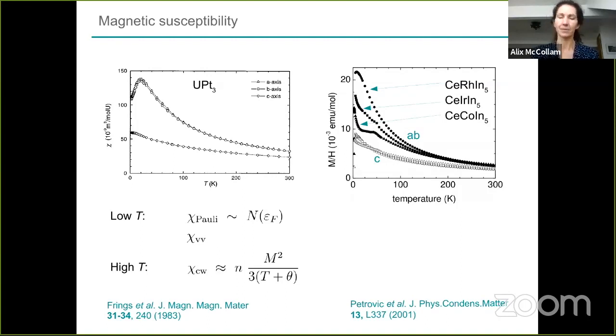So okay, let me clarify. When you measure the effective mass in the de Haas-van Alphen effect, you're measuring the temperature dependence of the Fermi function effectively, and that's where it's coming from. But that's for a Fermi liquid. If you don't have a Fermi liquid, you have a different form of the self-energy that goes into the expression for the de Haas-van Alphen effect. And it will give you maybe a slightly different temperature dependence, for example, but it still allows you to see the clear de Haas-van Alphen oscillations.